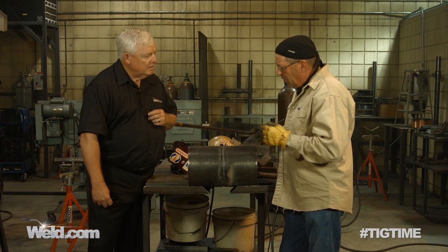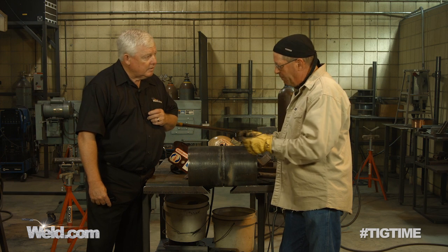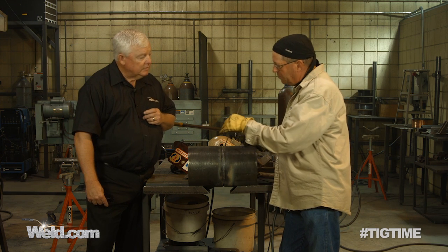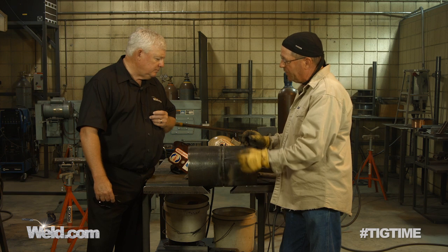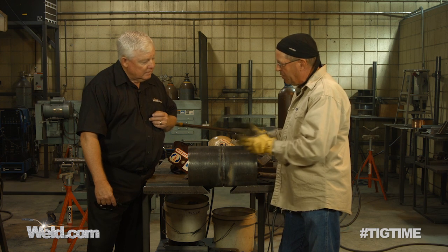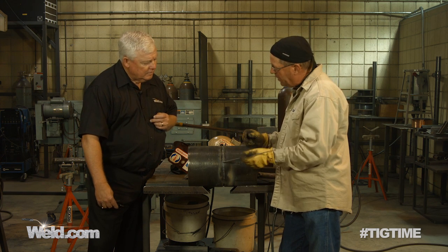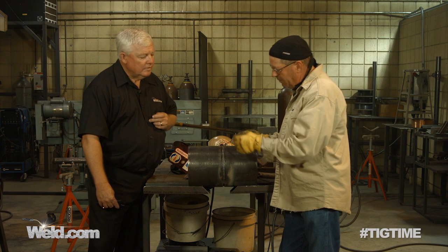Okay, so we had a fairly tight fit. We did a downhill root pass. We did a downhill hot pass to blow out any of our impurities. We did a fill pass. We kept everything clean on the way out, and we did a cap.